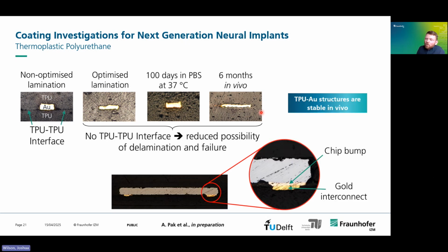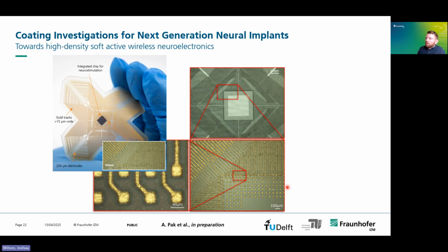And we can also assemble chips on these materials. So here you see a cross section with a chip, and what you don't see is the TPU because of the contrast. It's very transparent. But here, if we zoom in, this is the gold line from above, and here is the chip bump, and we can bring them together and interconnect. So we're able to assemble chips on these structures. And as a proof of concept, we have these devices with 15 micron, very high precision devices, 15 micron lines and spaces, and this chip integration as well.